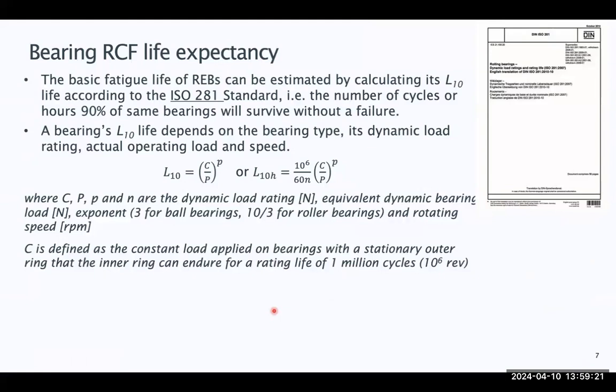The bearing rolling contact fatigue life can be calculated based on ISO standard 281, which takes into consideration the dynamic load rating, the operating load, and the type of bearing. If you know your bearing design and the dynamic load rating, which you can normally get from the bearing catalog, you can calculate under the particular operating load in a machine the expected life. L10 is the number of cycles or hours that 90% of the same bearings would survive without a failure. L50 means that 50% of the same bearings will survive without a failure, which is much longer than the L10.